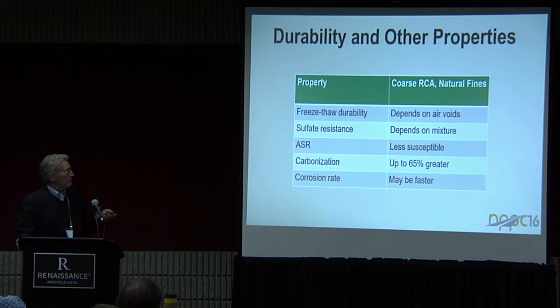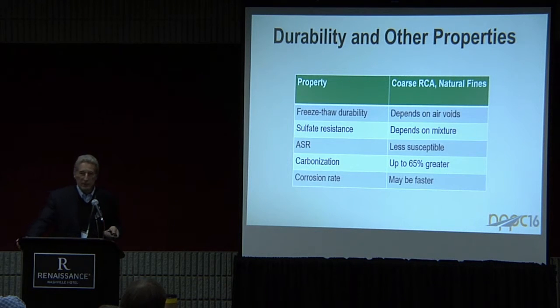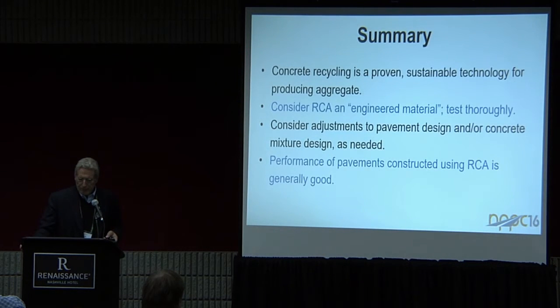Durability aspects really depend on the mix that you use. Freeze-thaw durability is primarily a function of the air void system that you develop in the new mix. ASR tends to be less susceptible because you've probably already consumed a lot of the reacting materials. As you saw in the Wyoming job, it's taken 30 years for it to start to show a problem now, whereas the original pavement was badly failed inside of 25 years. So those are the basic properties.